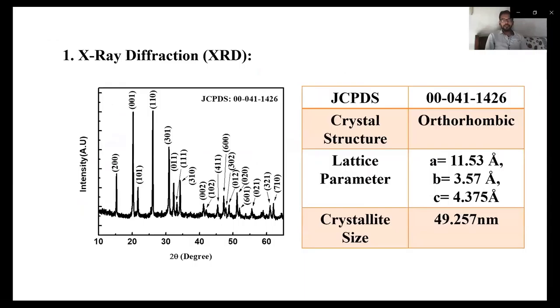The prepared material is characterized by various characterization techniques. The first one is X-ray diffraction. The X-ray pattern of the prepared material is well matched with the JCPDS card number 00-041-1426, and this shows that the crystal structure of the prepared material is orthorhombic. The lattice parameters are also calculated, where a is equal to 11.53 angstrom, b is equal to 3.57 angstrom, and c is equal to 4.375 angstrom. The crystallite size is also calculated by using the Debye-Scherrer relation.